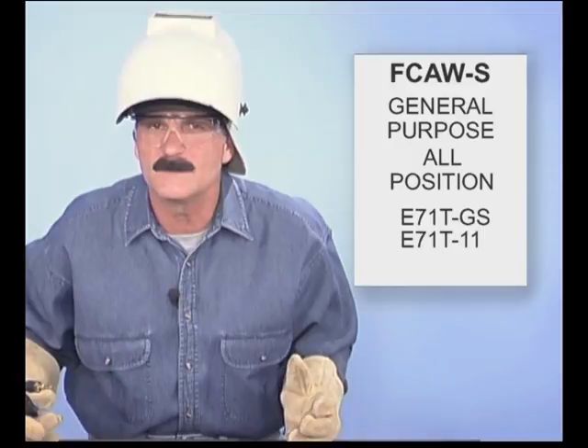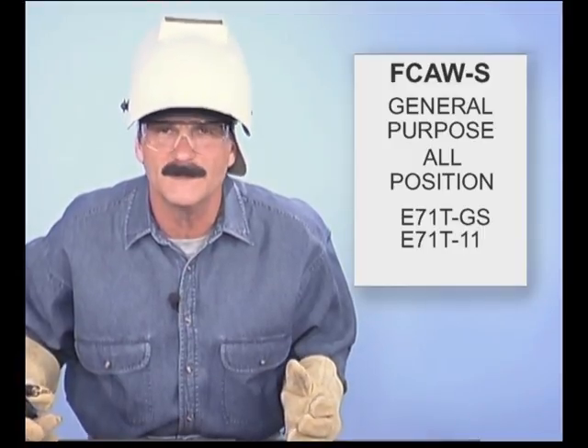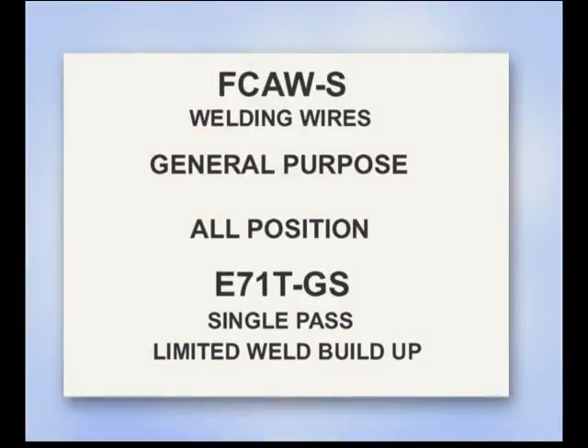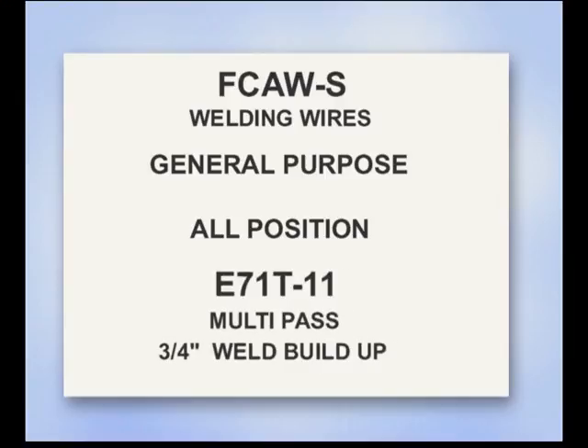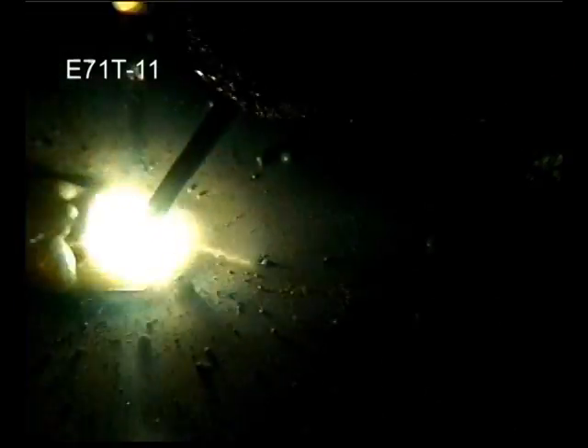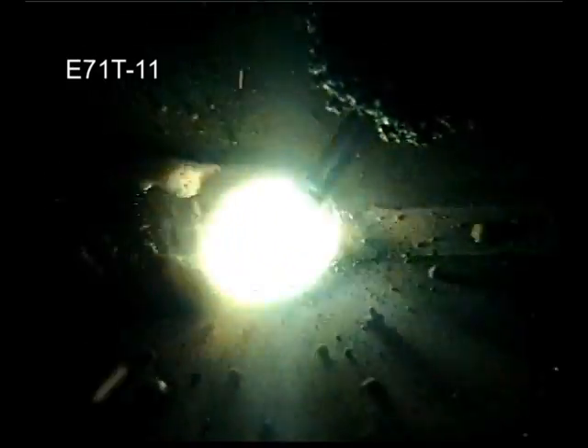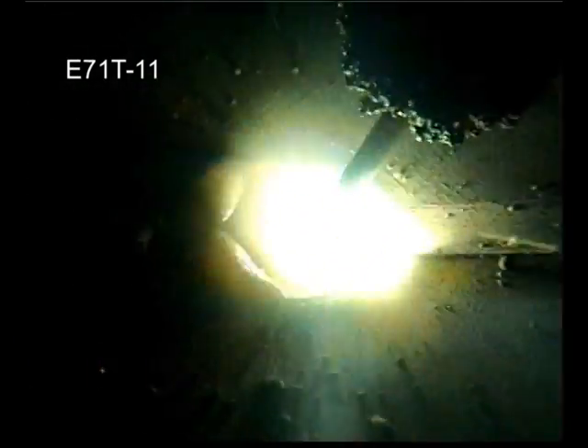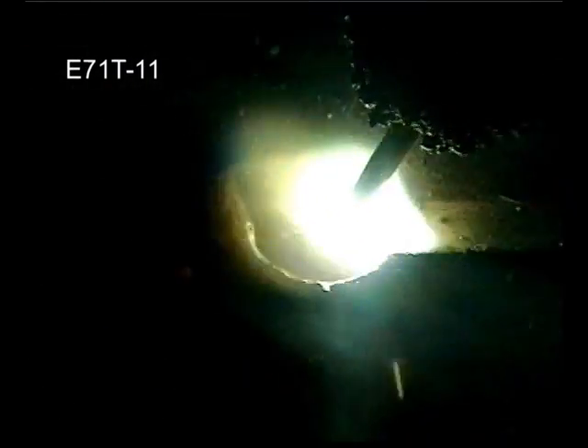E71TGS is often used with the lower voltage hobbyist type wire feed machines. These are recommended for a single pass weld with limits on the amount of weld buildup. E71T11, one of the most commonly used self-shielded wires, can be multi-passed, but is often limited to a weld buildup of 3/4 of an inch. With a smooth arc and spray metal transfer, E71T11 wires provide good weld fusion and are very easy to use in any welding position. This is the type of self-shielded wire we'll be using for our demonstrations.